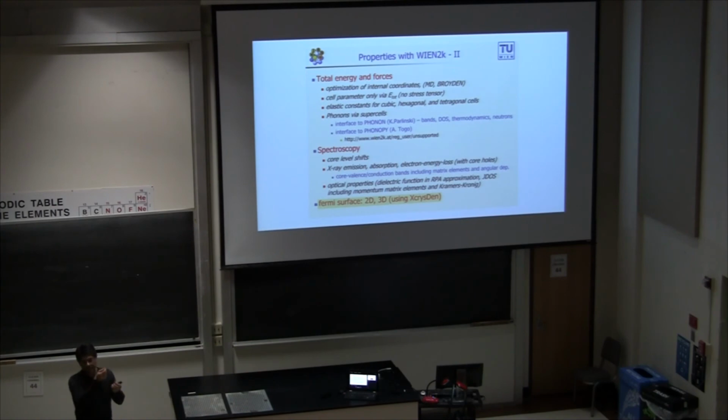You will see that if you do a minimization of the lattice energy for the tetragonal phase, you will get a lower total energy than for the cubic phase. So sometimes if it's difficult for you to distinguish one symmetry from the other, you can do these lattice optimizations by DFT, and it will tell you if the tetragonal phase is more stable than the cubic phase.